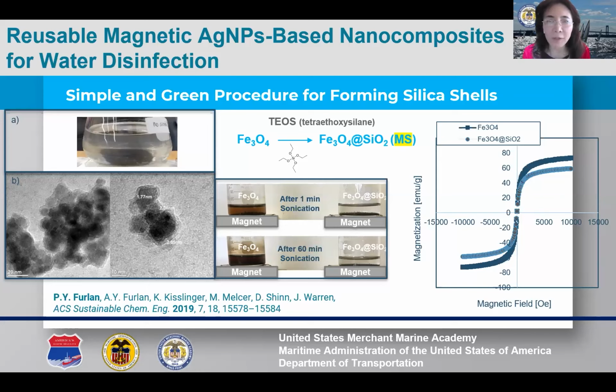The transmission electron microscope, or TEM, images on the left display the as-prepared MS nanoparticles, showing a uniform ultra-thin silica coating about 2 nanometers thick. The magnetic behavior, as shown in the right figure, indicated both the control and the silica-coated magnetite nanoparticles exhibited superparamagnetic properties, becoming highly magnetic in the presence of an external magnetic field and non-magnetic as soon as the field was removed. MS nanoparticles also displayed a very high magnetization of 59 emu per gram.